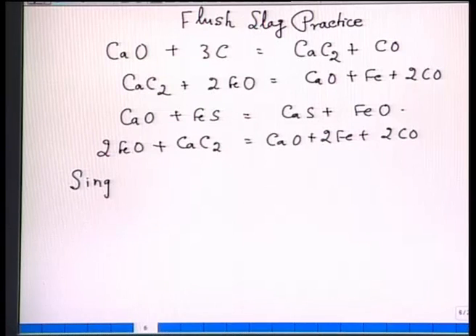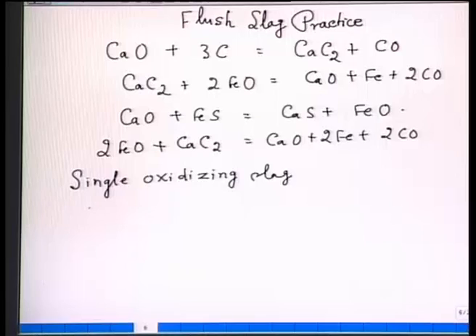That means, a single oxidizing slag is sufficient for removal of phosphorus. That means, if only phosphorus from hot metal is required to be removed, then a single oxidizing slag is sufficient. If sulfur and phosphorus both are required to be removed, then after removal of phosphorus, a reducing slag is to be created. So, that is how the refining and finishing operation is done in electric arc furnace. When this is over, then metal is tapped and cast for further processing operation.